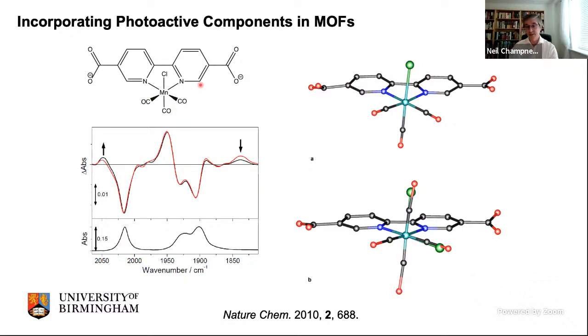The manganese complex is known to have higher quantum yields. And it should have a quantum yield of approximately 30%. And that would be enough for us to actually follow this process by single crystal X-ray diffraction. And we can certainly follow it by infrared spectroscopy. And in fact, this works. So approximately 30% of the manganese centers isomerize from the FAC to the Mer isomer. And we can even do this on a single crystal.